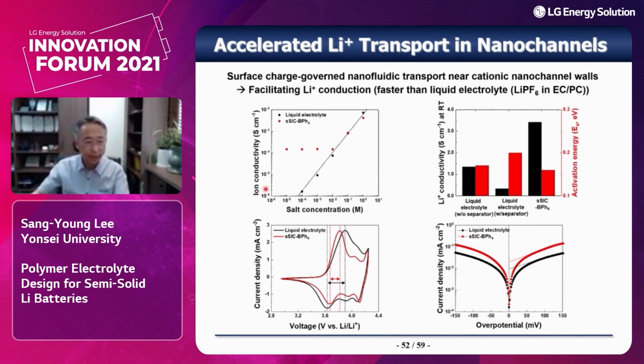Okay, so if we measure the ionic conductivity in terms of salt concentration, up to 10 to the minus 2 molar, there is little difference between the liquid electrolyte and our electrolyte. However, if you further decrease the salt concentration, you can find a large gap between the two electrolytes. In other words, our electrolyte shows higher ionic conductivity than the liquid electrolytes. This was due to the surface-charge-governed nanofluidic transport near cationic nanochannels.